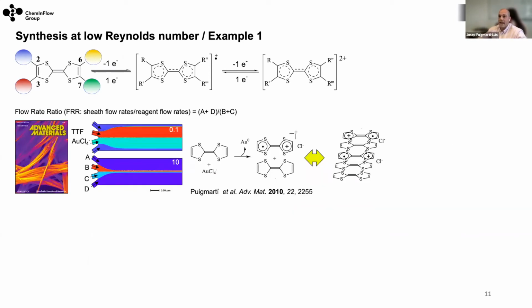And this is actually the first paper. I was working with TTF, so the first paper I published working with microfluidics is this one here. Obviously, I work with the TTF, but look at this now. We are using the bare TTF, so we don't have any functional groups there. And what we do is this oxidation reaction. So the TTF oxidizes, we reduce the gold salt, and what we have is the formation of this charge transfer salt.